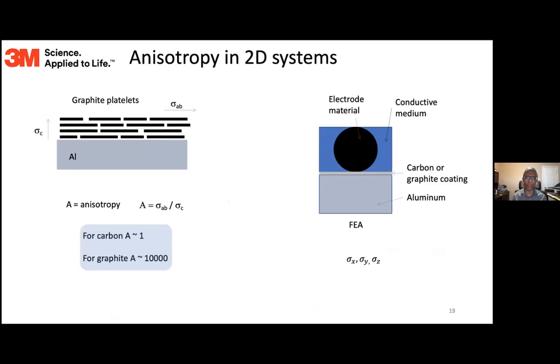So we call it an anisotropic material. That's imparted to the material by the geometry and the atomic arrangement, and that makes a huge difference for these devices. For example, in most of these layered materials, in the XY plane, current is conducted way better than in its perpendicular direction, which is what we call the C direction. In an isotropic material, that conductivity ratio is 1. That's why we call it isotropic: it conducts equally in every direction.